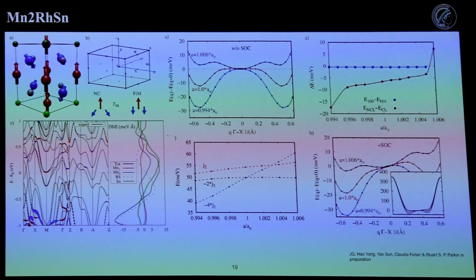And then we also looked at some other things, such as the spin-orbit effect, such as how non-collinear it is as a function of strain, and what's called the magnetic crystalline anisotropy. We looked at how the energy changes between 2 different directions. And you see the magnetic crystalline anisotropy is actually very weak. When it's positive, it's out of plane.